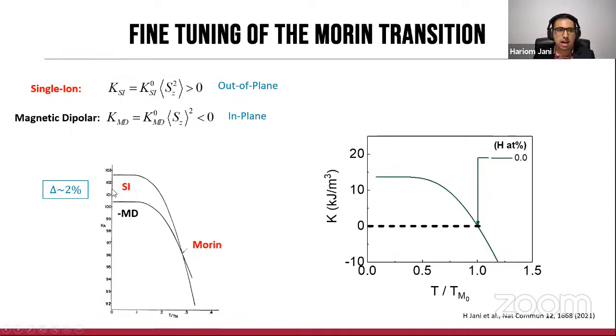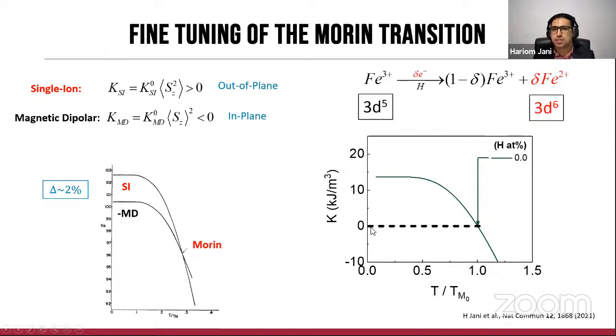So shown here are the two single ion and magnetic dipolar terms, one favoring out of plane, one favoring in plane orientations, and the total K, the total anisotropy, basically follows this evolution here, going from a positive value to a negative, which as we know corresponds to an out of plane to in plane transition. Now, when hydrogen is added, there is a slight shift towards Fe2+, which effectively changes the fraction from a 3d5 dominant state to a 3d5 dominant plus a small fraction of 3d6 states. And this makes all the difference here.